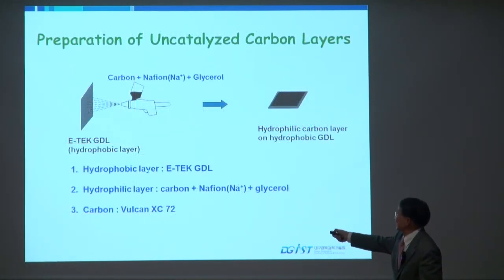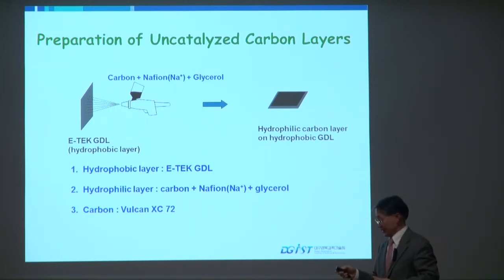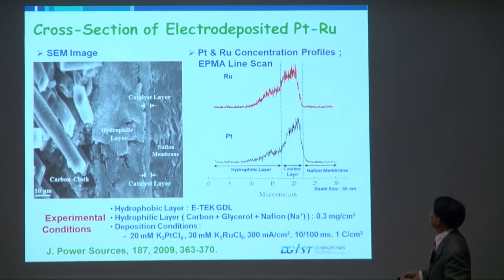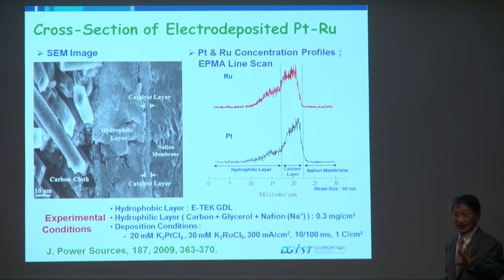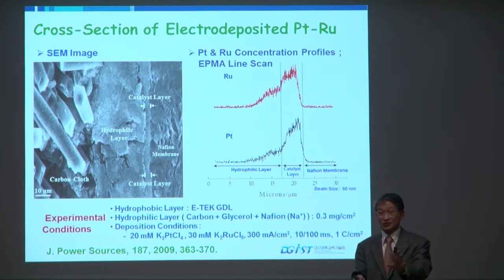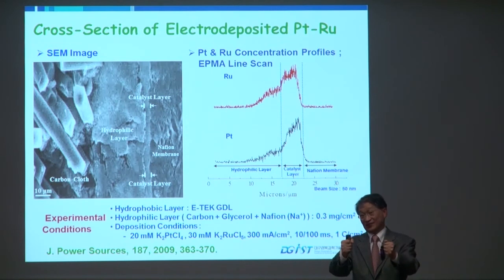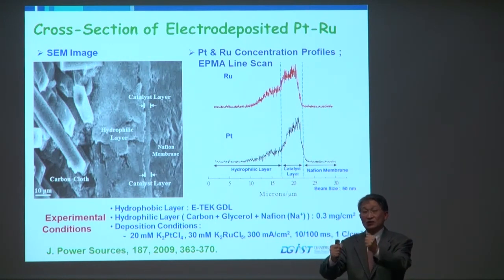Hydrophilic, hydrophobic layer, this one, hydrophilic layer: carbon, Nafion, glycerol, and use this. We just spray this, then a hydrophilic surface is very easily obtained. Then electrochemical deposition, and I'm now talking about the platinum-ruthenium part. In platinum-ruthenium co-deposition, the standard potential is different, so you have to control the concentration ratio to end up with a suitable atomic ratio of platinum and ruthenium.